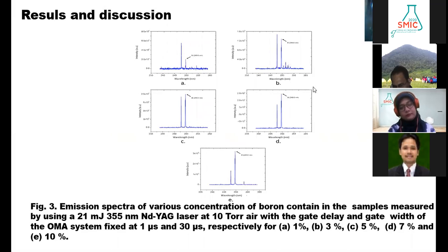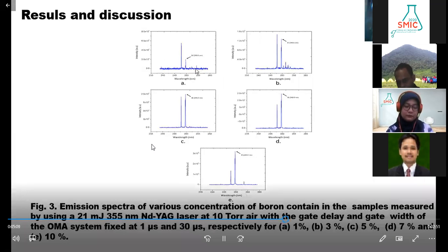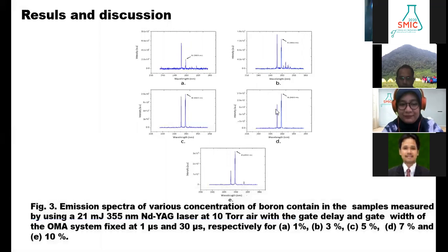In all of these spectra, we can see clearly that the emission line of the boron is very sharp. We use the boron emission line as an indicator that the borax can be detected by this experiment. This is the emission of boron, and this is the emission of carbon from the flour material. And boron, of course, comes from the borax in the sample. Also, we can see if the concentration of boron increases, the intensity of the boron emission also increases. The same takes place for 5%, 7%, and 10%.